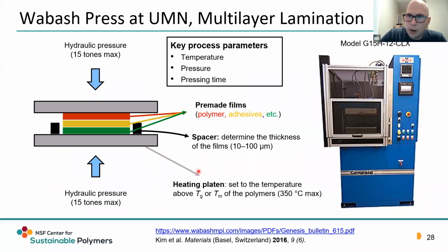What you can further do with this is if you have some pre-made films, either made from spin coating or from pressing them as films previously with the compression molder, you can laminate films and look at adhesive properties, diffusion between the layers, or some other interactions at the interface that you might find interesting. Again, the same kind of controlling parameters are your temperature, pressure, pressing time, and you want to consider the Tg or Tm of the materials you're working with to derive what process parameters you want to use.